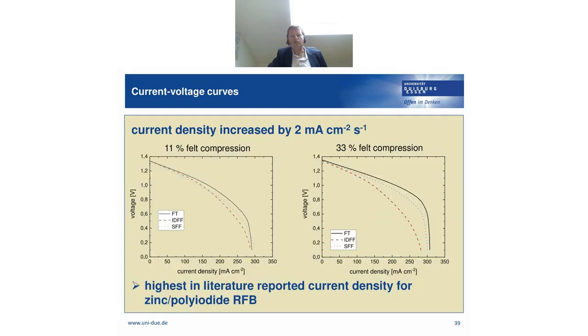So then we recorded current voltage curves for these three flow fields in the 100 square centimeter cell. And we varied the felt compression. So this is the electrode compression here in the left graph, it's 11%, in the right graph, it's 33%. But regardless of the felt compression, always the flow field, so relatively simple flow-through design yielded the best performance. So for this concentration here, we have current densities of several hundred milliamps per square centimeter. And this is really so far the highest literature reported current densities for this kind of battery.